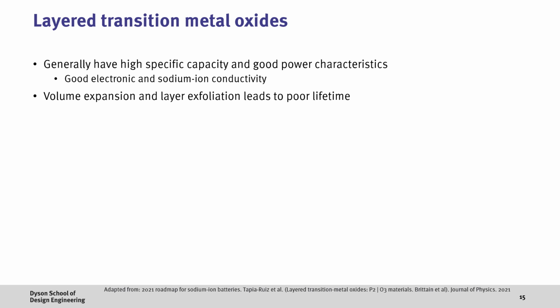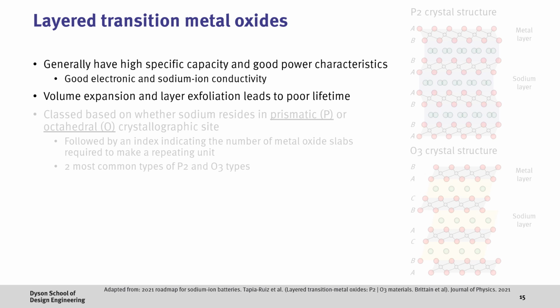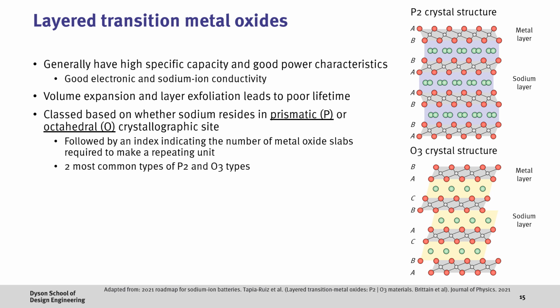However, as we insert and remove sodium ions, this can lead to reasonable volume change and poor lifetime if not managed. Here, there are two main types of layered transition metal oxides, which are classed based on whether sodium resides in a prismatic or octahedral crystallographic site. These are therefore termed P and O type materials, followed by an index which indicates the number of metal oxide layers needed to make a repeating unit, with P2 and O3 type cathodes the most common.